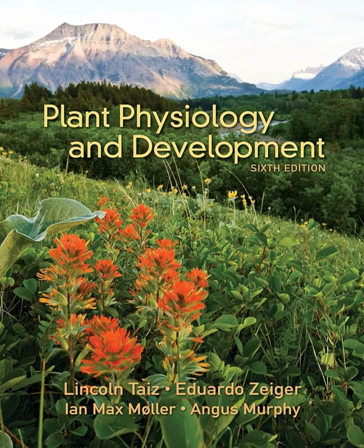Exactly. But link the same glucose units with a different bond, a beta linkage, and you get cellulose, incredibly strong, rigid, indigestible for us, perfect for building structures. Link them with yet another bond, beta-1,3, and you get callose, which is involved in wound responses. So just changing that one chemical connection completely alters the molecule's shape and function. That's fascinating, just a tiny tweak in the chemistry. It really is, and it applies to all the different wall polysaccharides. The specific linkages determine their shape, how they pack together, how they interact with water and other polymers, and ultimately their role in the wall.